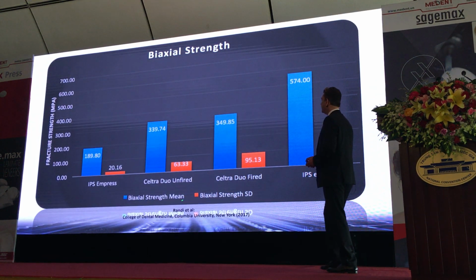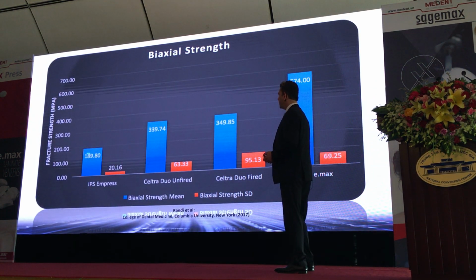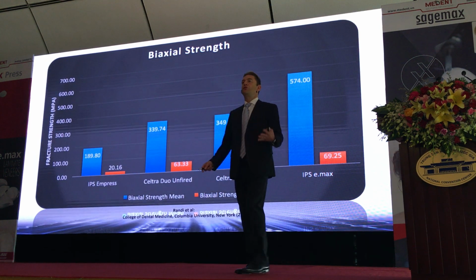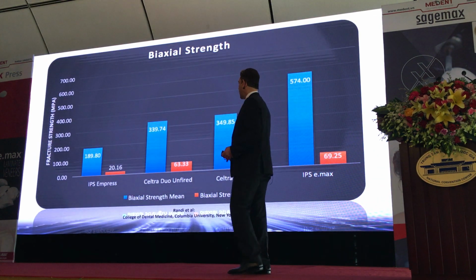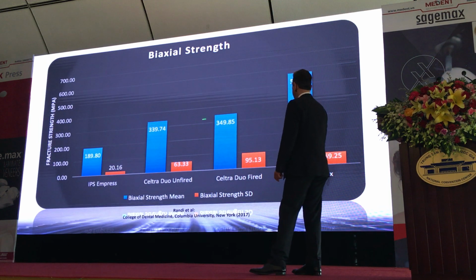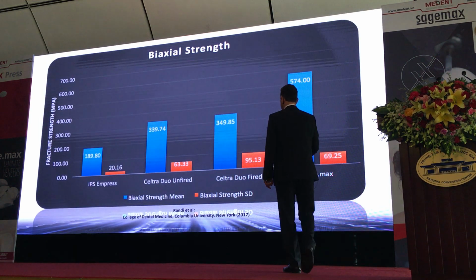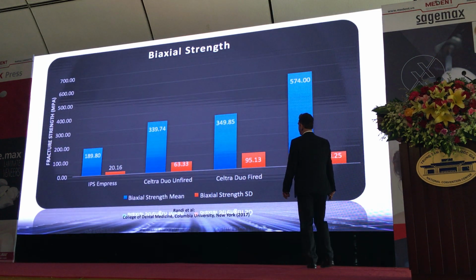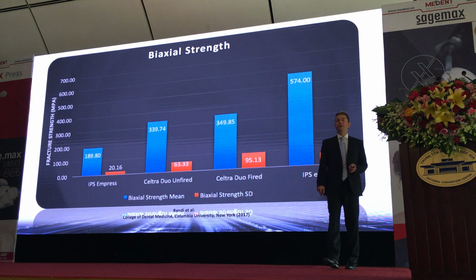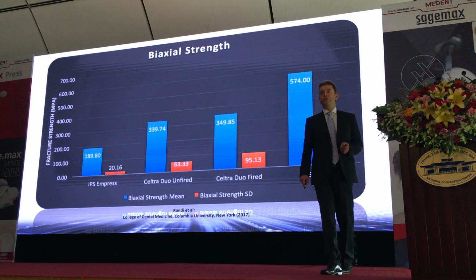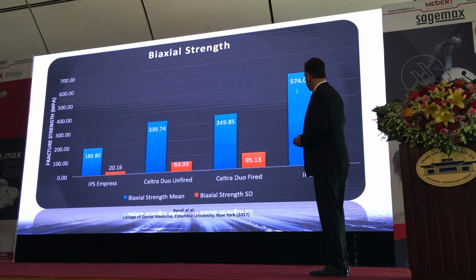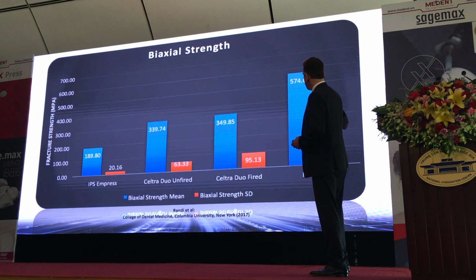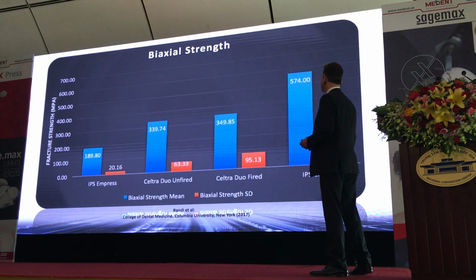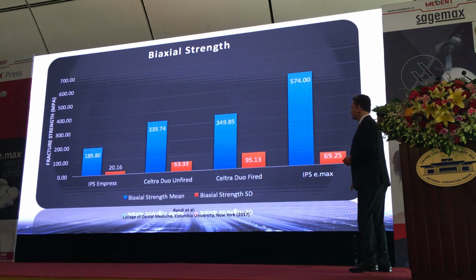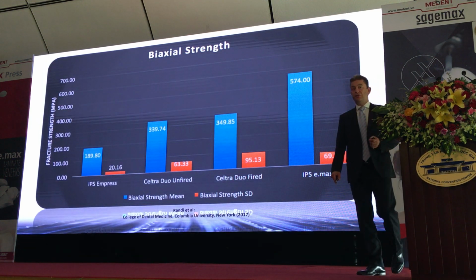So you can see now, if you look at the blue bars, this is the flexural strength, the mean flexural strength. And you can see Empress, because Empress is not so strong, right? It's on the lower side. And you can see the different kinds of Celtra material, which is in the range of 340 or 350 megapascals of flexural strength. But emax, on the right-hand side, you can see is significantly higher flexural strength, with more than 500. So this is 574 megapascals, which is much higher than Celtra.